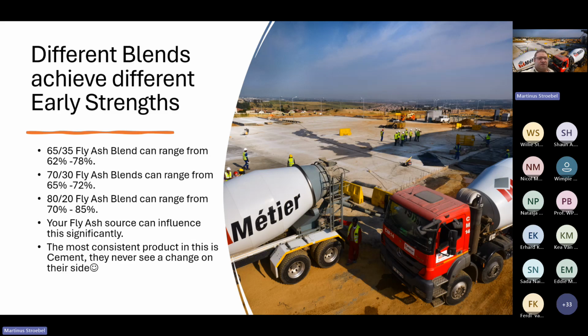In short, I've just tried to summarize this. If you do a 65-35 blend with fly ash, I'm not even touching on slag currently, you can range anything from 62 to 78% at 7 days. Now, if you as a contractor plan your life that you need 70% at 7 days, and you've priced for the cheapest concrete and you get 60%, you will not be happy with the ready-mix supplier.